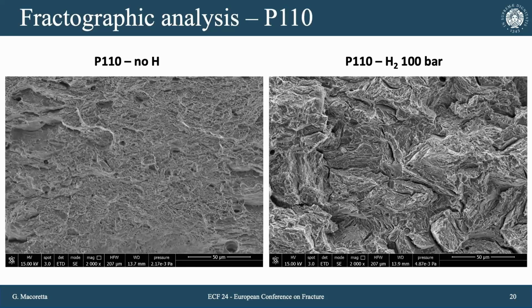On the P110, the situation is even more evident. We pass from a surface with ductile features, so even in this case microvoid coalescence and so on, to a surface with a strong transgranular fracture and even some traces of intergranular fracture. This is a high-strength material compared to the previous one, and so the effects of hydrogen are still more evident compared to what happened in the other materials.